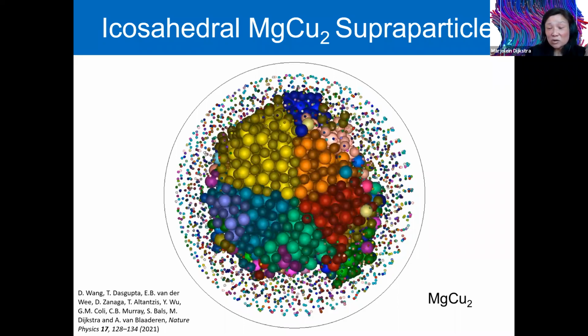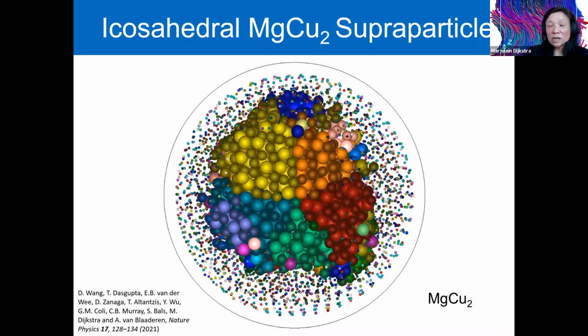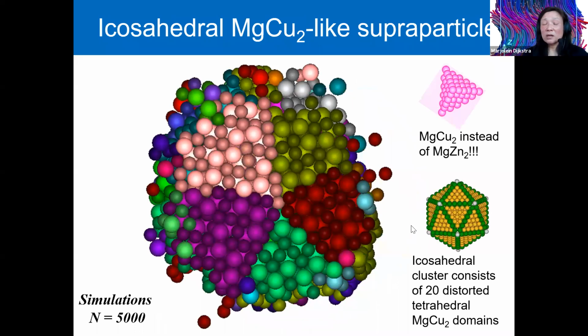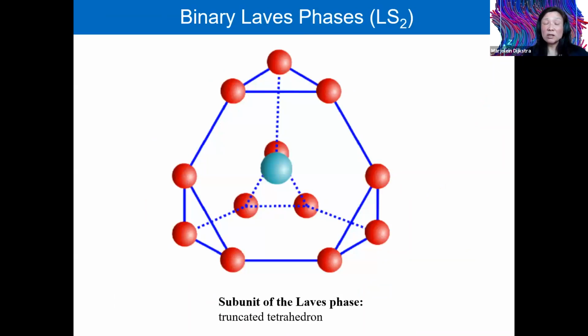What is very interesting here is that if you look at the tetrahedral domains, they now consist of magnesium copper phase instead of the magnesium zinc phase, which was the most stable structure in the bulk phase. To understand why the crystal structure changed from magnesium zinc into magnesium copper phase, we should have a look at the subunit of these Laves phases.